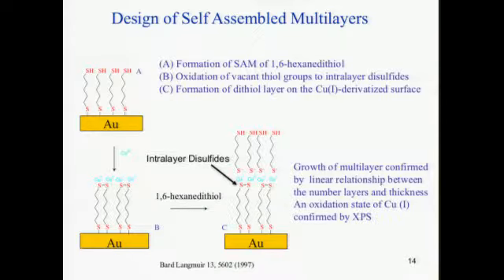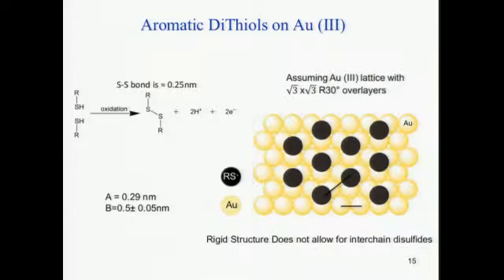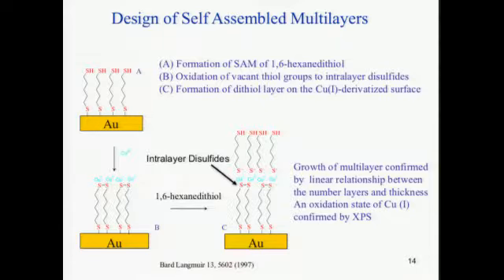In this case, we discovered that it's actually not, you shouldn't say in experiments it's not what we want, but it really wasn't what we wanted, or they wanted, because I wasn't there. But what they found is that you actually form what is called intralayer disulfide bonds here. Which is very interesting. But how is it possible with the alkane thiol? I should say just some properties about alkane thiols.